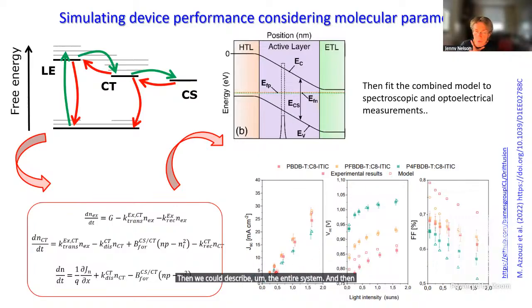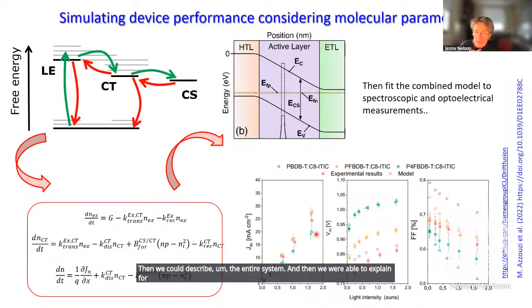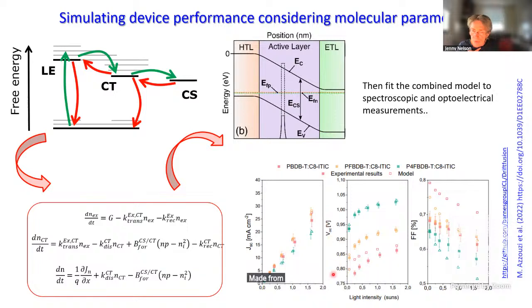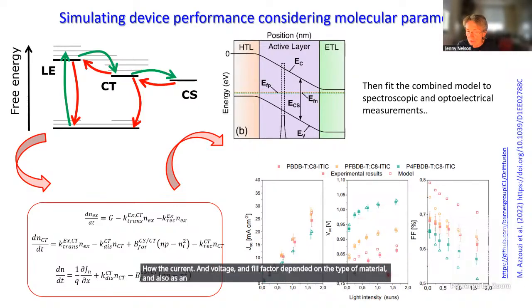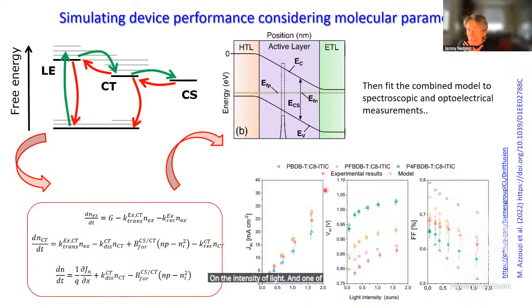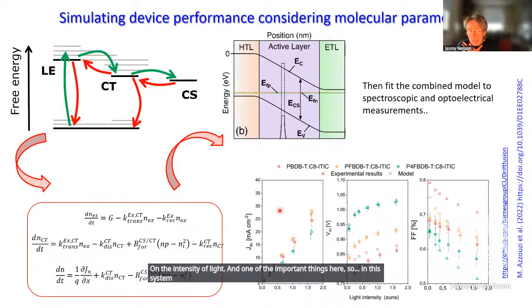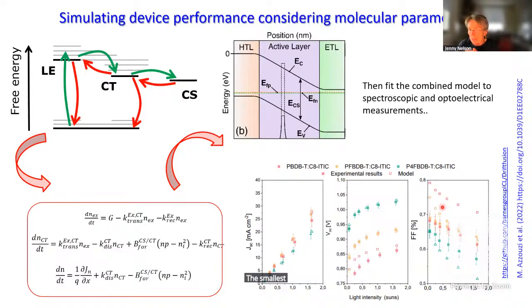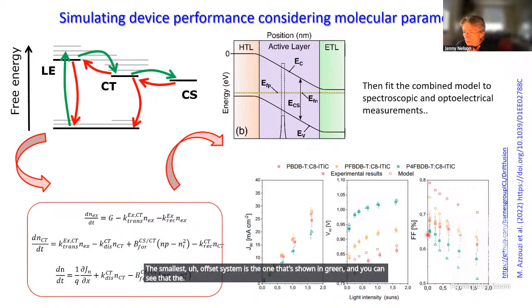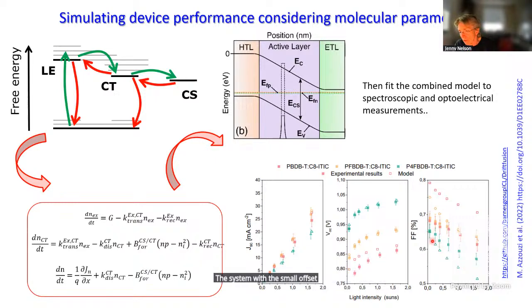And then we were able to explain, this is just an example, a set of devices made from different materials that we studied. We were able to explain how the current and voltage and fill factor depended on the type of material, and also, as an extra parameter, on the intensity of light. And one of the important things here, so in this system, the smallest offset system is the one that's shown in green, and you can see that the system with the small offset was then suffering from a poor fill factor.